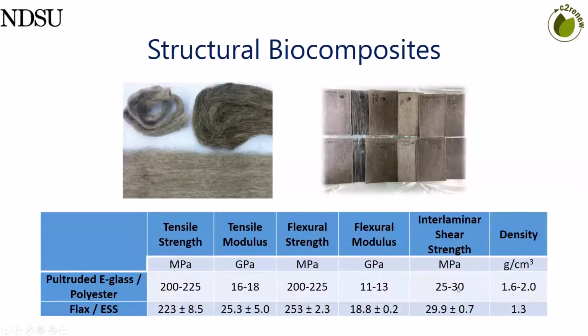and interlaminar shear strength, so the resistance to failure between plies of those fibers. That's interesting in itself, but when you look at the density of the two composites, these gains are even more attractive on a specific basis, because your specific tensile strength and specific modulus are going to be even higher than your traditional material.